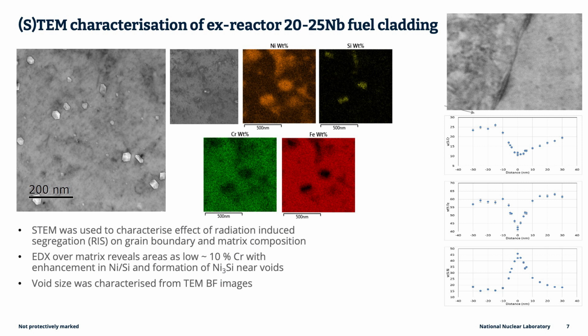And yeah, there's just an example here of a grain boundary profile down to, like I say, those 10% sort of numbers. And the map also shows the different spatial distribution of silicon there, so we can tell that we've got nickel 3 silicide precipitation at pre-existing dislocation loops, and also just nickel segregating rather more diffusely to those areas as well.